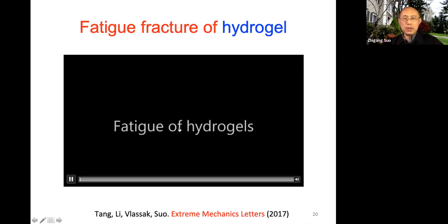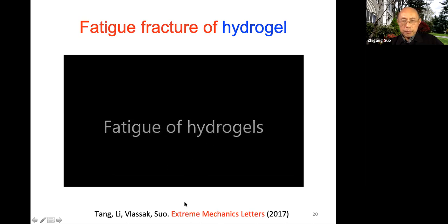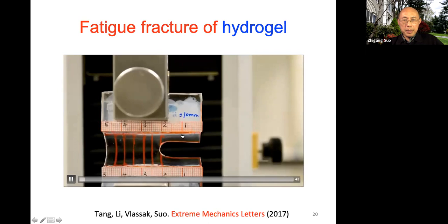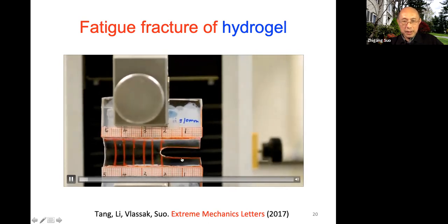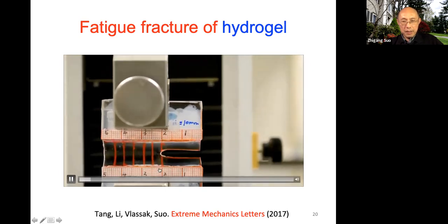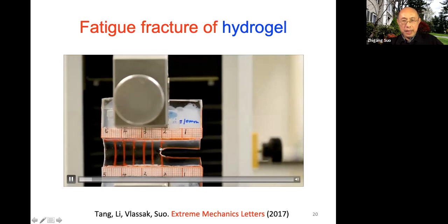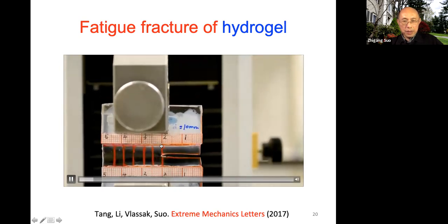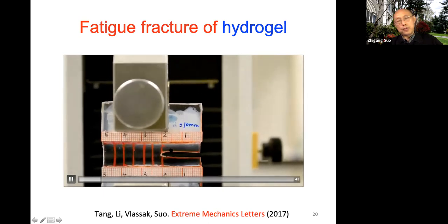So here is a gel in front of a reality. So, fatigue of a hydrogel. So here is an experiment. This material is transparent. Again, this is a black background and a beautiful piece of material. And we stretch up and down, cyclic loading. And before we do the experiment, we already put red marks here so we can watch whether the crack moves ahead or not. So far, the crack doesn't move ahead, but that's only a few cycles.